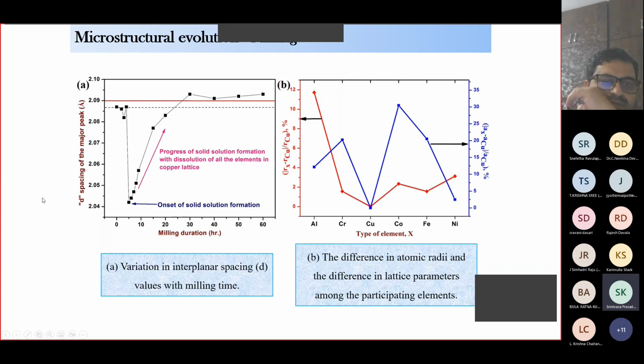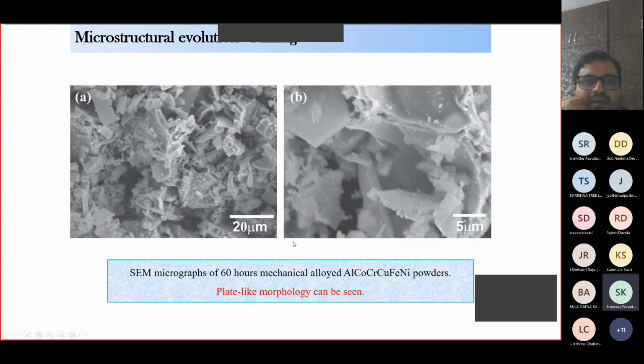And then we try to track the formation of the structure here, solid solution formation, using the measurements of D spacing, that is interplanar spacing, with respect to the milling duration. We figured out where exactly the solid solution forms and where exactly the saturation happens. And we also measure the variation in the lattice parameter and variation in the atomic diameter, how they help, how they affect, and so on.